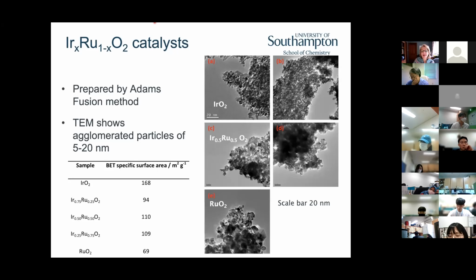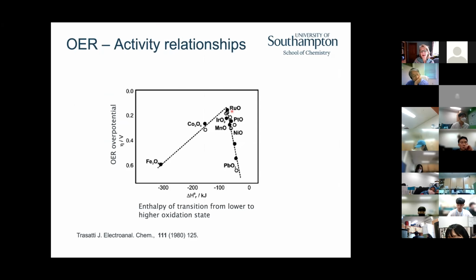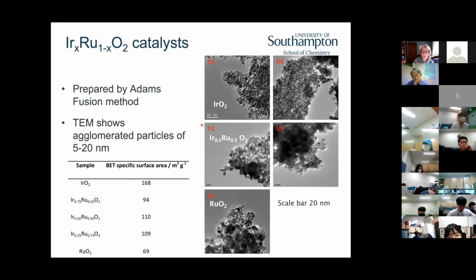But he made a series of iridium ruthenium materials. Ruthenium oxide should be the most active, and that's been known for a very long time for the oxygen evolution reaction, but it's not very stable. So what we tend to do is add iridium, which is less active, but more stable. And he made this series of samples. And the nice thing is that we were able to keep the particles pretty small.